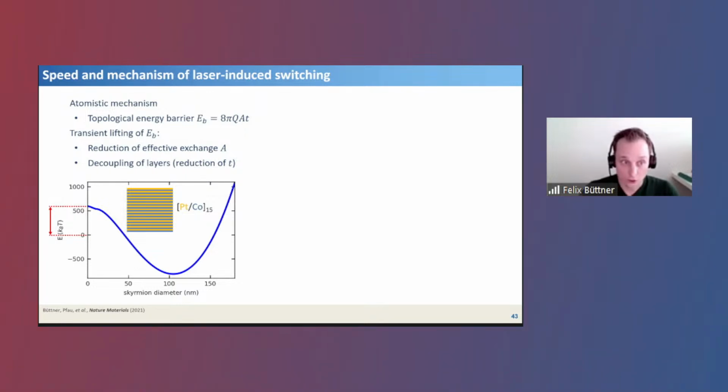Not over the Curie temperature, because there you have no order, but just below it, we find a phase where the exchange constant is very low, so you can have rapid changing of topological charge, because that energy barrier is essentially zero, but you still have enough exchange to produce order over a few spins, enough to have a seed for a magnetic skyrmion.